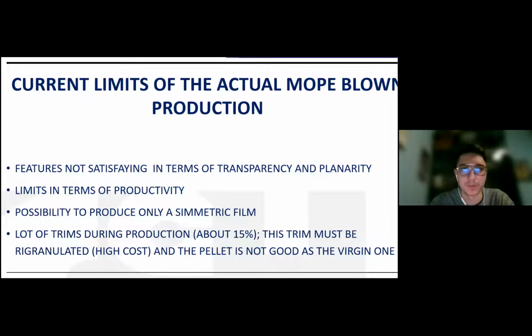Now we'll show you some of the current limits of the actual MOP blown production, because the production of MOP film right now is basically only in blown lines. And we have a film that is not satisfying in terms of transparency and planarity. We have limits in terms of productivity if compared with the cast line, for sure. Possibility to produce only asymmetric film, and a lot of production of trims that must be regranulated, so we have high cost, and the pellet is not as good as the virgin material, for sure.